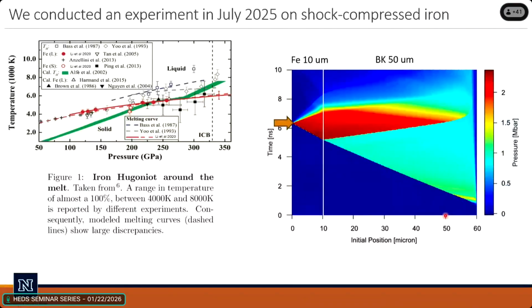We did a run on 10 micron iron with an ablator in front of it. So a standard shock: 50 micron of plastic, 10 micron of iron. We shock the system, send the shock through.